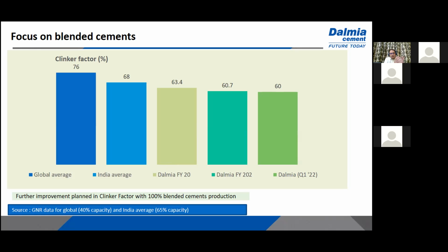If you see, as compared to the globe, India has been doing quite well. The clinker factor globally is 76%, and in India, it is 68%. So by this, we can say that we are doing better on circular economy levers as far as raw material is concerned. And at the same time, we are also helping other industries. For example, this clinker factor is reduced by use of waste, other cementitious materials from the industry, such as fly ash from the thermal power plant, blast furnace slag from the steel industry.